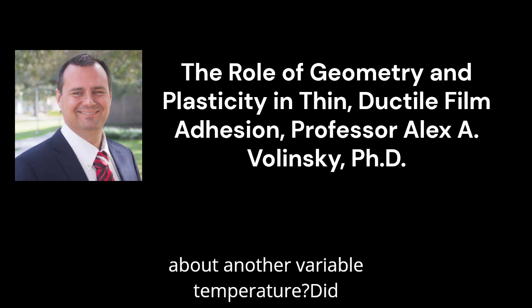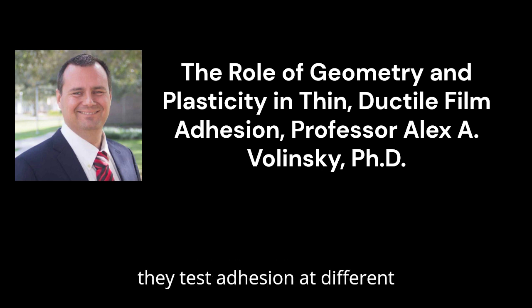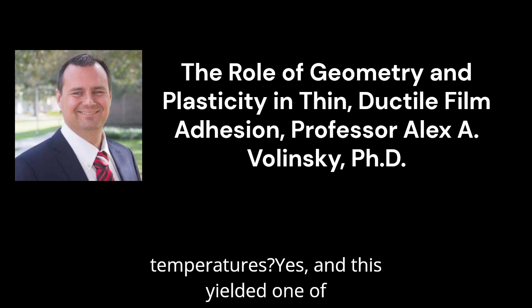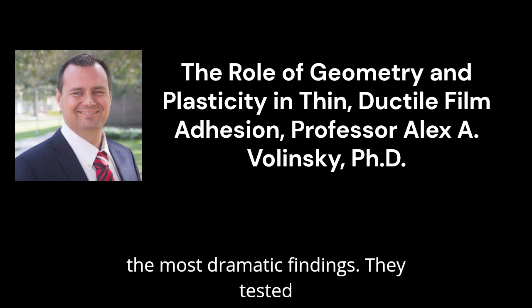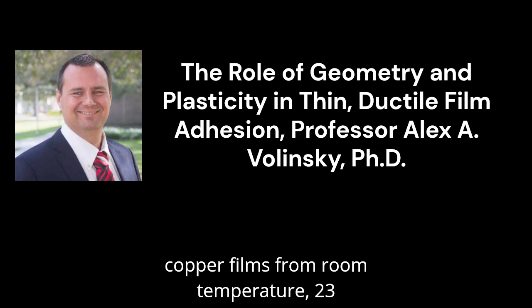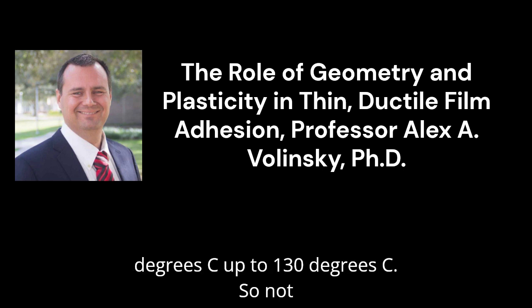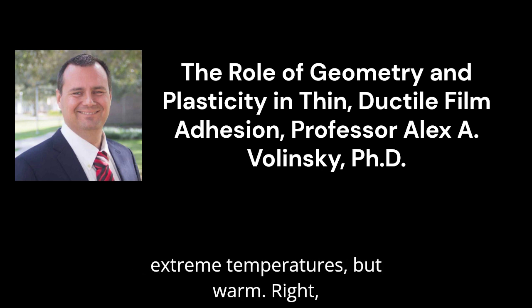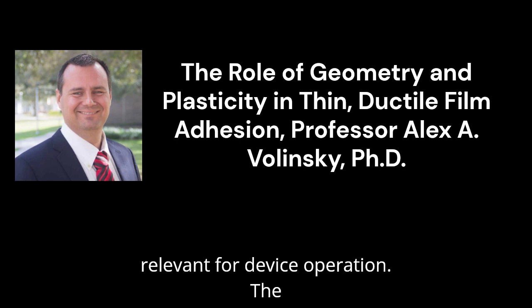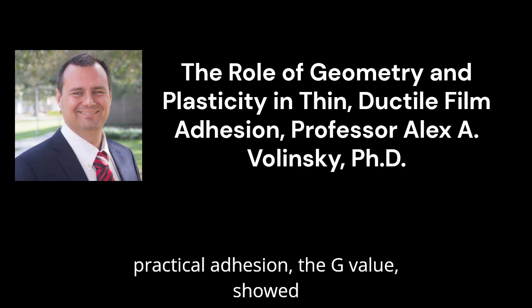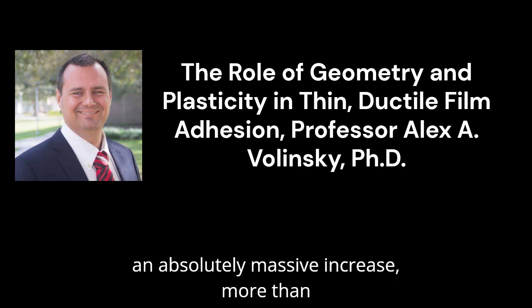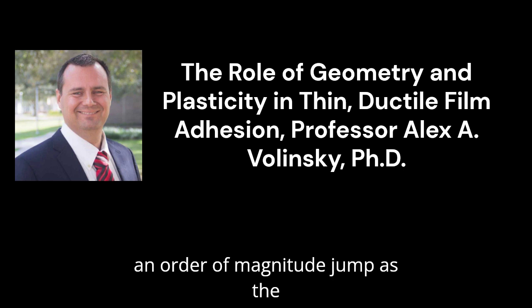Okay, what about another variable, temperature? Did they test adhesion at different temperatures? Yes, and this yielded one of the most dramatic findings. They tested copper films from room temperature, 23 degrees C, up to 130 degrees C. So not extreme temperatures, but warm. Right, relevant for device operation. The practical adhesion, the G value, showed an absolutely massive increase, more than an order of magnitude jump as the temperature rose.